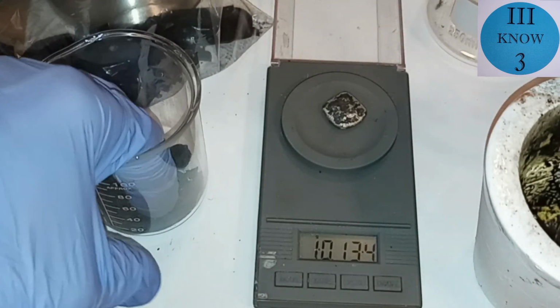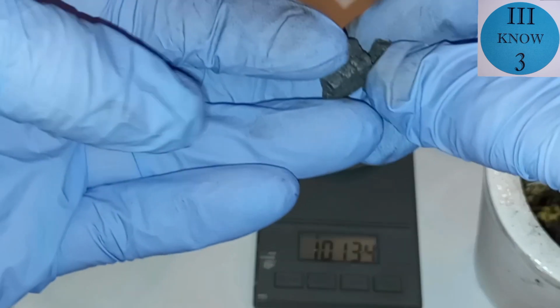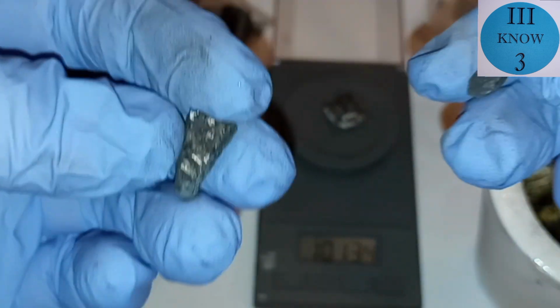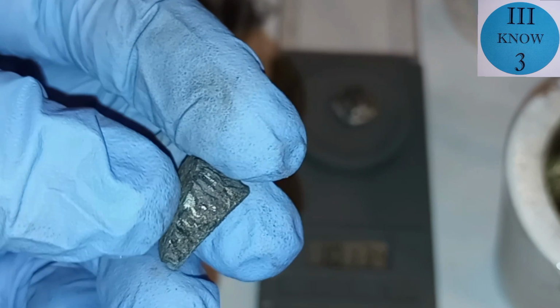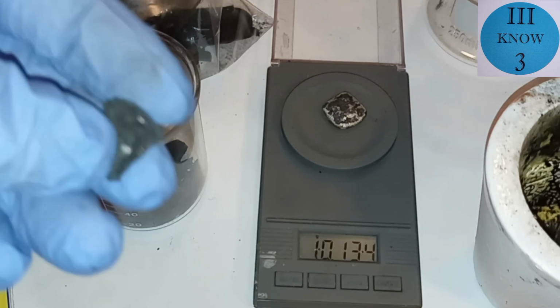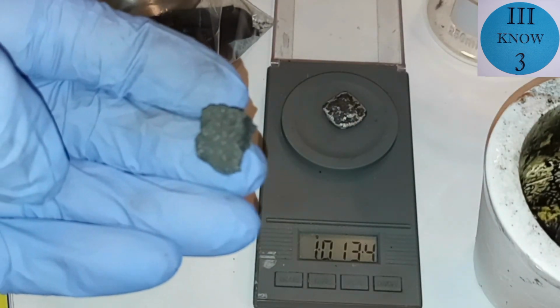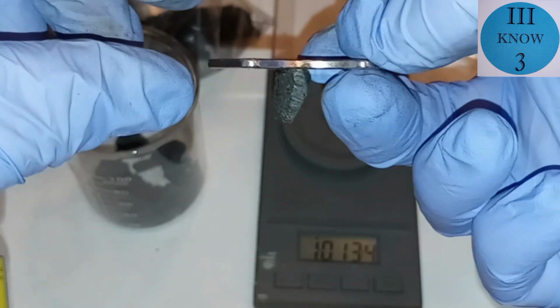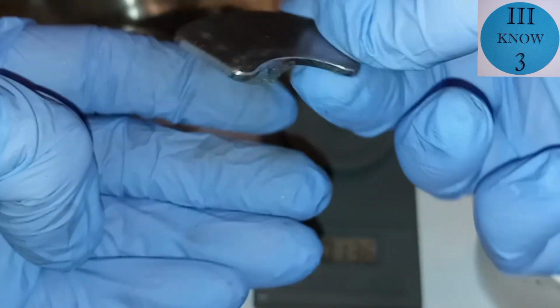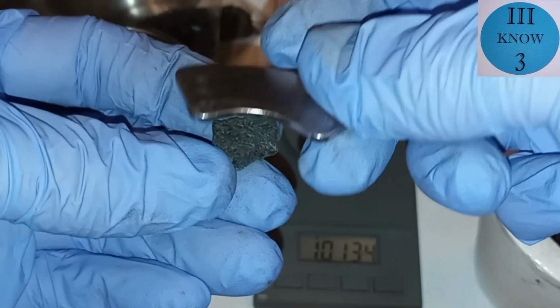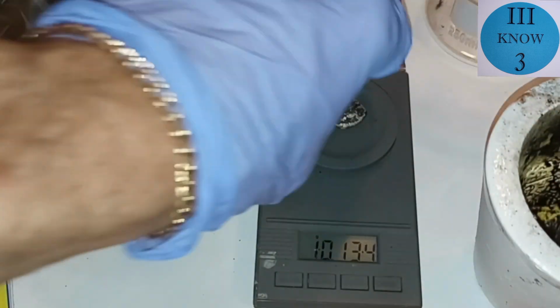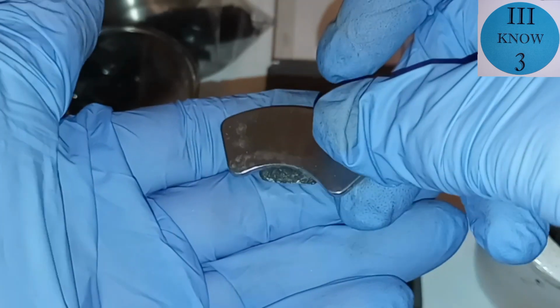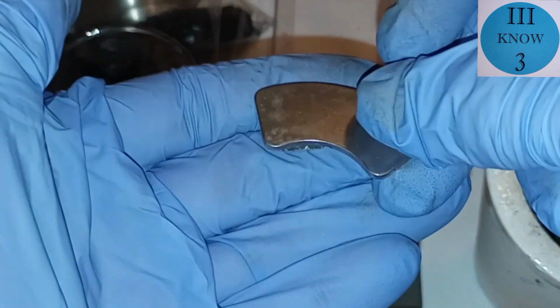Now, what I think happened is with the addition of the sulfur, we turned those base metals into sulfides. And I don't know if you can see the grain structure in there, but that could be any number of different sulfides from the base metals. And one interesting thing about this material is it's very slightly magnetic. It's not as magnetic as like a piece of iron, like a nail or something, but it's definitely still magnetic. The silver button, the collector metal button that we have, is not magnetic at all.